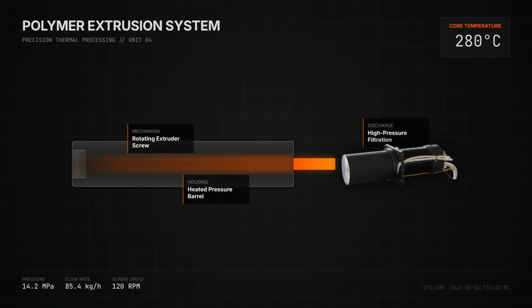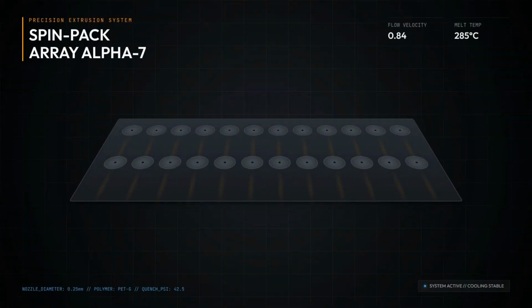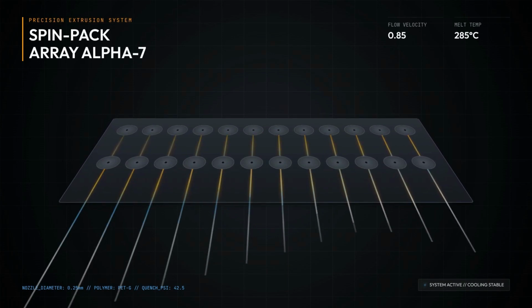The clean, dry PET enters the extruder. A rotating screw transports, compresses, and melts the material at temperatures typically around 280 degrees Celsius. The molten PET then passes through fine filtration systems to capture any remaining microscopic particles. A gear-type metering pump delivers an extremely accurate and nearly pulse-free flow. The purified PET melt reaches the heart of the plant, the spin pack.